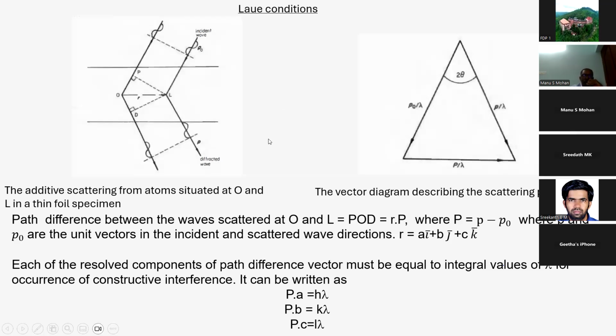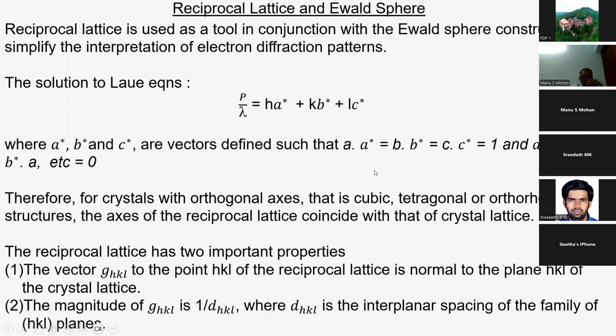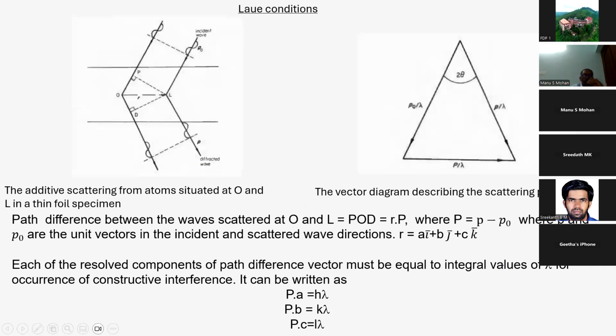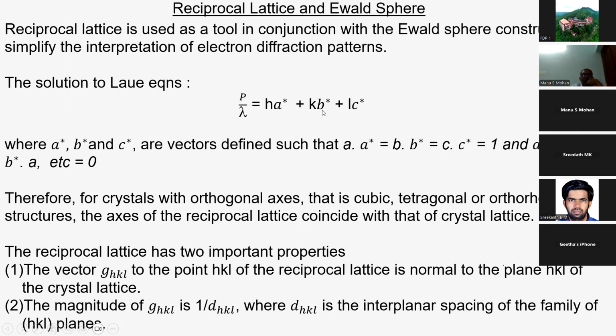So here also, P by lambda is the path difference between the two rays. If you take 2D, P by lambda should be - and P by H or P by lambda should be an integral multiple of this wavelength. Then only you get the reflection. So P by lambda has been equated to H A-star plus K B-star plus L C-star, where A-star, B-star, C-star are the reciprocal lattice vectors, and these reciprocal lattice vectors have a relation A dot A-star equal to 1.